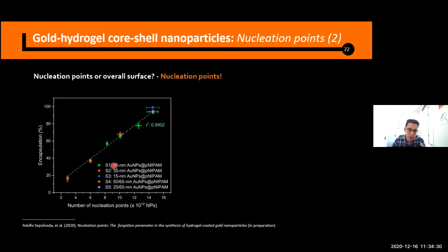We perform different polymerizations with different particle sizes because in the literature, most of the authors mention that what is important in this type of synthesis is to control the overall surface, in this case the gold surface, that is in the solution, in the synthesis itself. But here what we are showing is that no matter what size of particles we are using, if we control the number of nucleation points, we can tune the encapsulation yield at specific values.